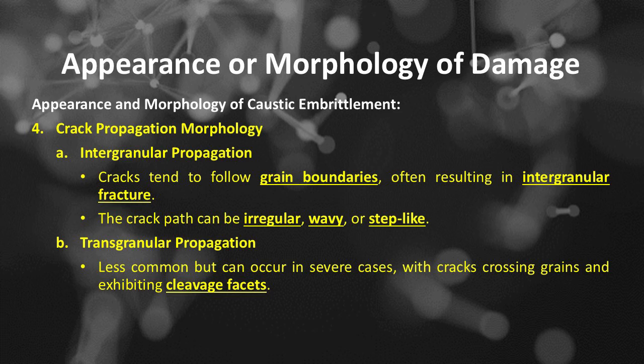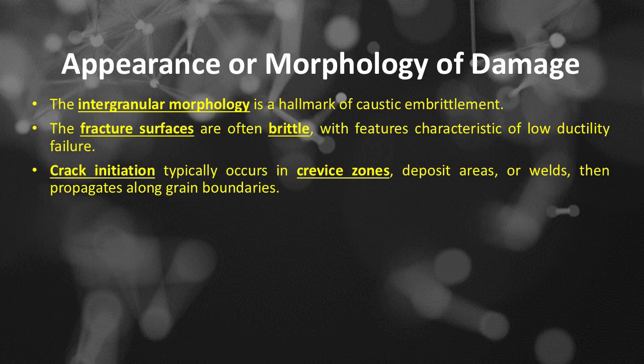Number 4 is crack propagation morphology, which includes, number A, intergranular propagation. Cracks tend to follow grain boundaries, often resulting in intergranular fracture. The crack path can be irregular, wavy, or step-like. Grain boundaries may appear widened or etched due to corrosion. Number B, transgranular propagation. Less common but can occur in severe cases, with cracks crossing grains and exhibiting cleavage facets. The intergranular morphology is a hallmark of caustic embrittlement. The fracture surfaces are often brittle, with features characteristic of low ductility failure. Crack initiation typically occurs in crevice zones, deposit areas, or welds, then propagates along grain boundaries.